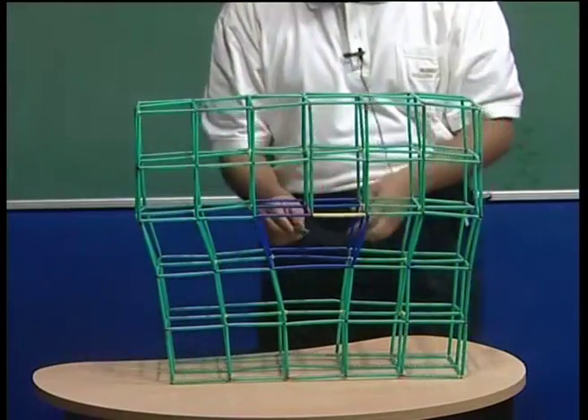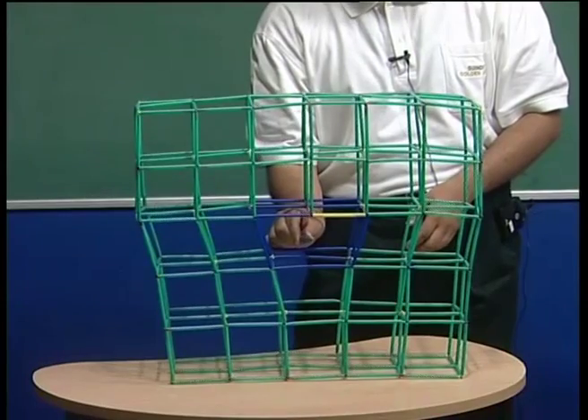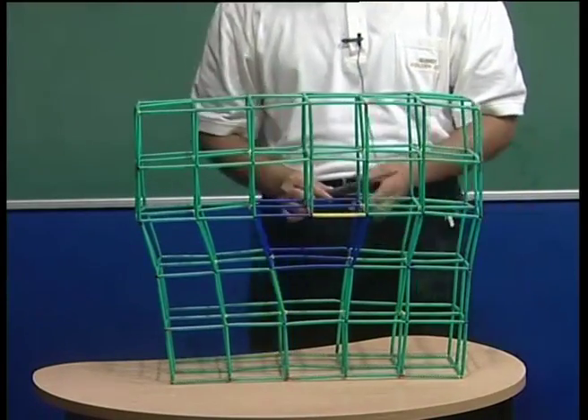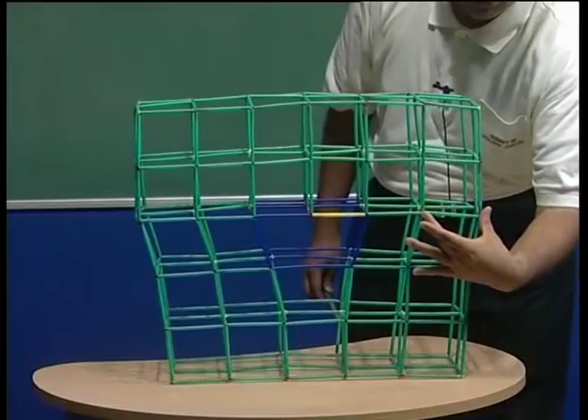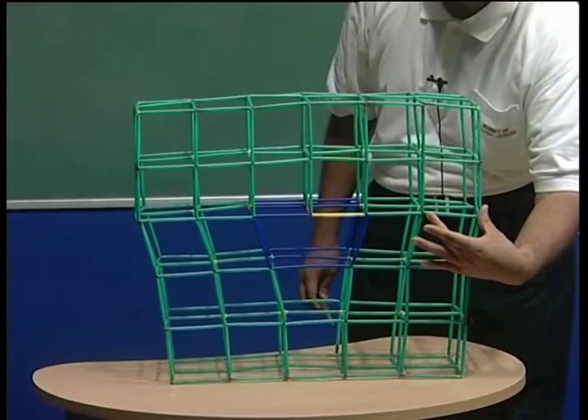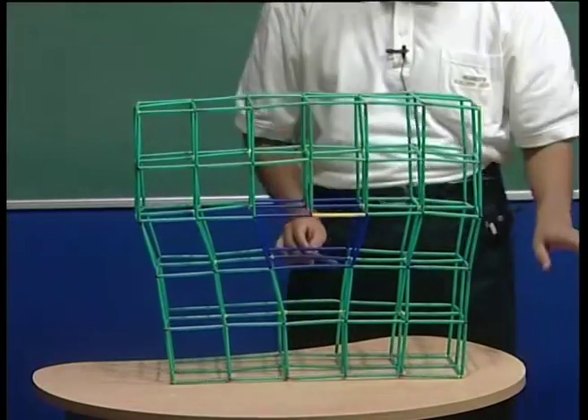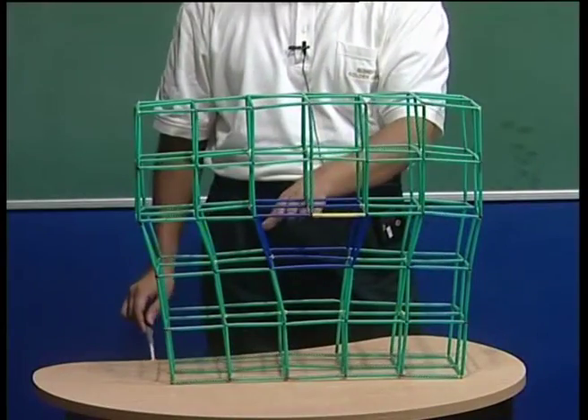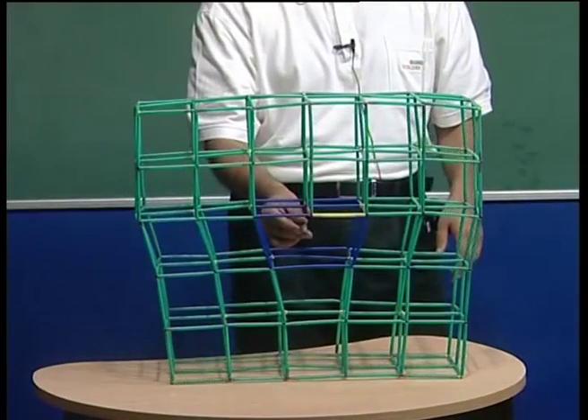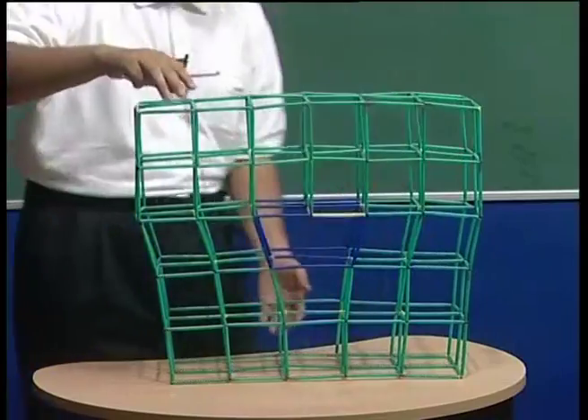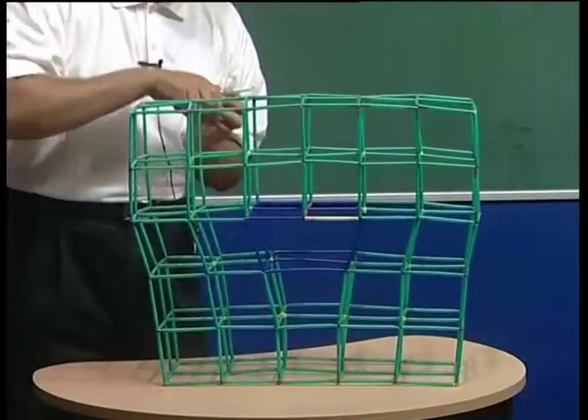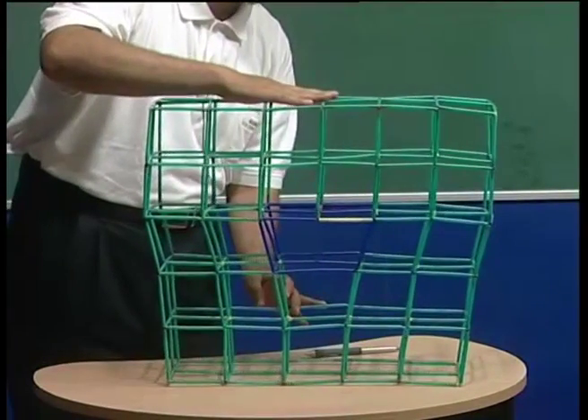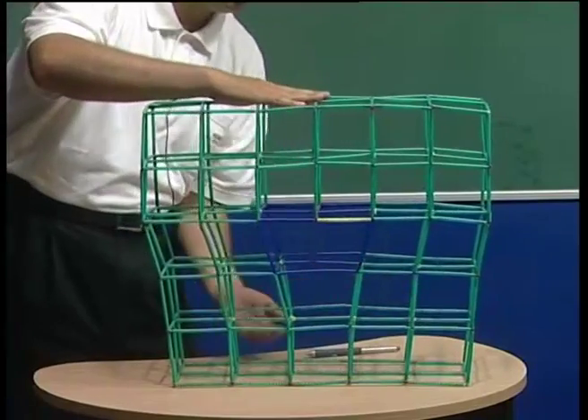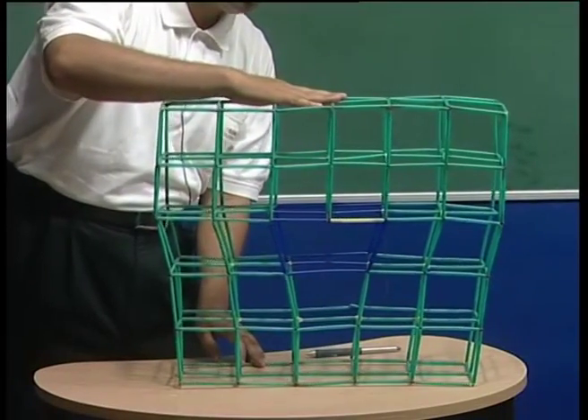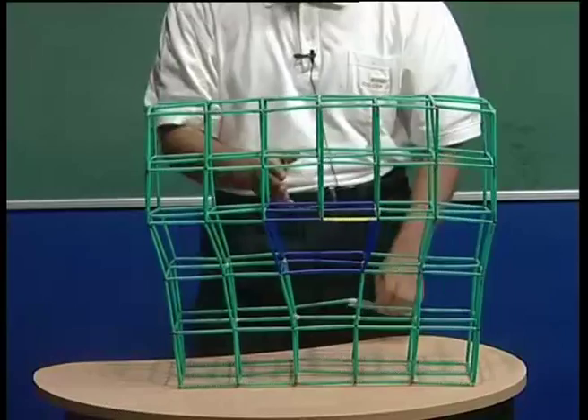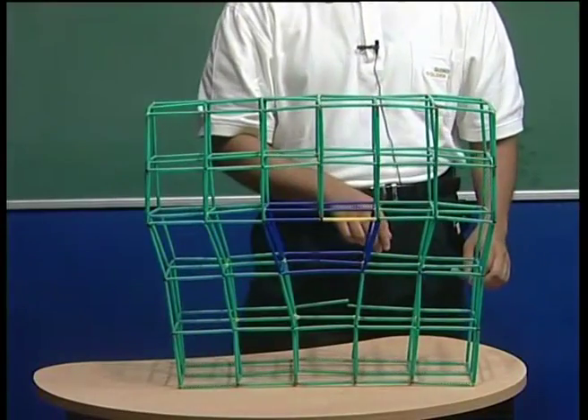Second thing, it is associated with the line vector, which is between the missing and the extra half planes. It is associated with the Burgers vector, which is a lattice translation vector connecting two lattice points. The T vector and the B vector together define the slip plane along which this dislocation line can move. So if I had to shear this crystal, for instance, I apply a shear on the top like this, and of course I pull the bottom side to apply a shear like this, then what would happen to this crystal is that this dislocation would move on the slip plane.